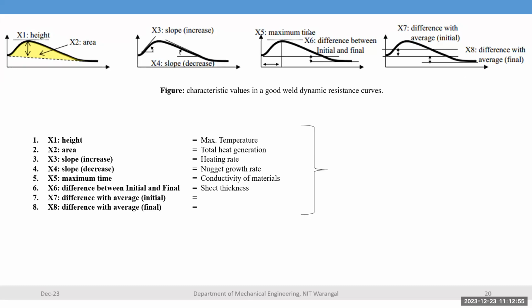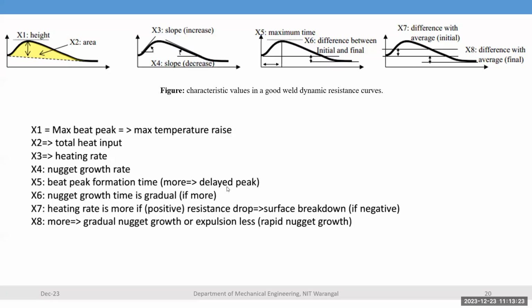So without defining all these things, all the curves look the same, but you may not get the perfect data. So the maximum temperature, total heat generation, heating rate, nugget growth rate, conductivity of material, and sheet thickness. These 8 variables reflect temperature, heat generation, heating rate, growth rate, conductivity of material, and sheet thickness. So x1 is the maximum temperature rise, and x2 is the total heat input. X3 is the heating rate, and x4 is the nugget growth rate.